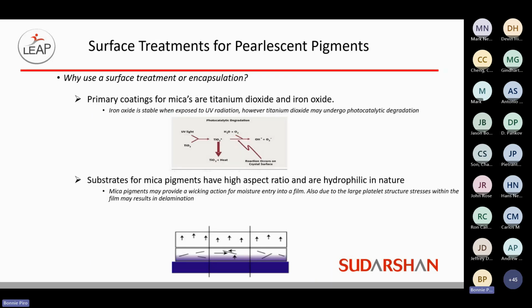Micas can be surface treated for different types of reasons. In the silvers or the TiO2 coated ones, as we've talked many times, the photocatalytic degradation of the TiO2 is important to consider, especially in the very, very fine particle sizes of the silver micas, and when there is not a clear coat over top. These might require some additional surface treatment to be able to combat that degradation of the TiO2.